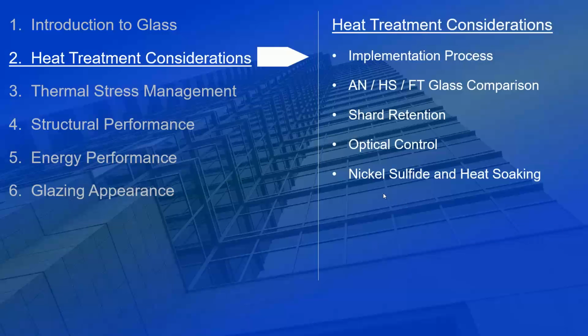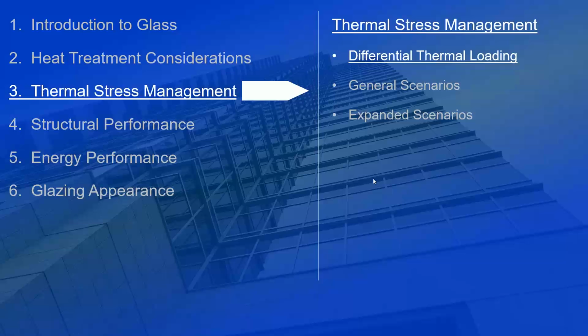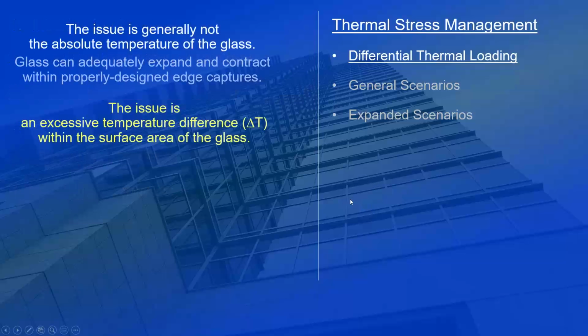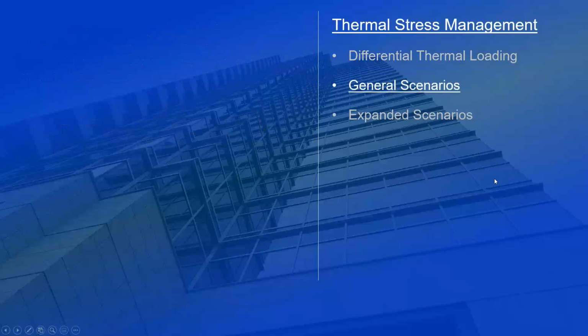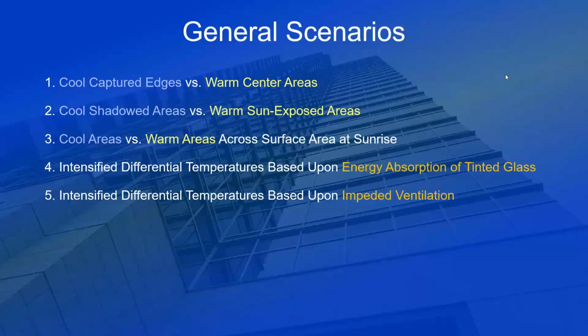Moving on to thermal stress management. When we talk about thermal stress, the concern is the excessive temperature difference, or delta T, within the surface area of the glass. Some scenarios that we typically see are cool captured edges versus warm center areas, cool shadowed areas versus warm sun exposed areas, cool areas versus warm areas across the surface area at sunrise, and intensified differential temperatures based upon energy absorption of tinted glass.